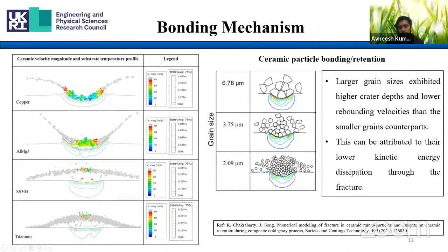To see whether a ceramic particle is retained on the substrate surface, Rohan Chakrabarti with his group did some simulations on different substrate conditions from softer to harder, and he saw that on harder substrates the retention was minimum, but on softer surfaces the retention was there. As we all know, when a ceramic particle strikes with very high velocity, either it ruptures, fractures into fragments, or it deforms very minutely. The retention of these ceramic particles on the softer surface they connected with the crater depth. The more the crater depth, the better the retention.